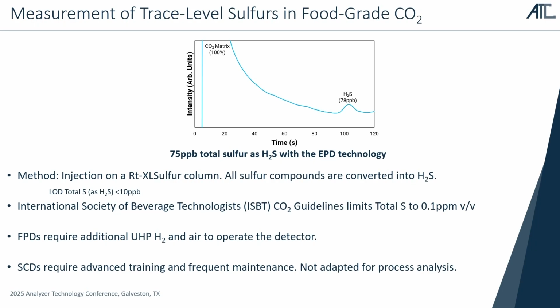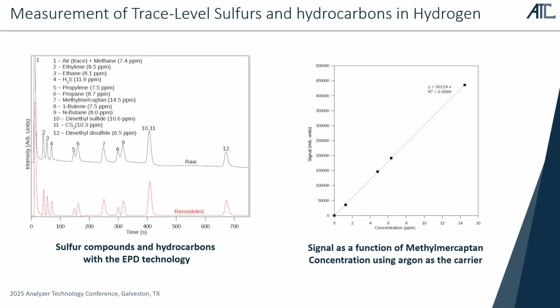And the final test I wanted to show is total sulfur in CO2, because there's a Coca-Cola standard that requires less than 0.1 ppm total sulfur in food-grade CO2. So we can measure H2S and total sulfur in CO2 down to the ppb level without any issue.